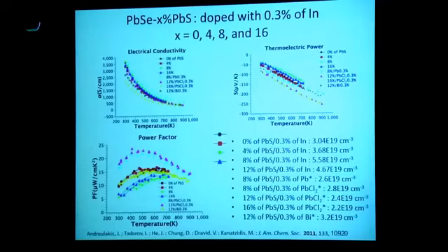investigated the N-type system first. And here's just some data. I know it's a lot of data. Don't pay attention too much to the numbers, but this is just to show that it's well behaved from the doping perspective. You can put lead chloride, make it N-type. You can put indium, and indium can go into the lead side. Chloride can go into the selenide side, and you can put carriers in there. So essentially, you can control the number of carriers with these dopants, and here's the conductivities.